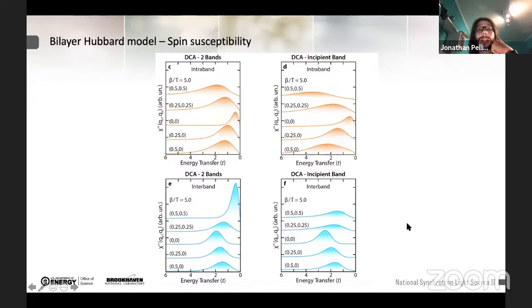What we could observe is that the intraband spin susceptibility presents the conventional dispersion of spin excitation in magnetic material, which has zero energy at the gamma point, at zero, zero, and then it increases in energy. Whereas the interband pocket presents an antiphase dispersion. But most importantly, look at the difference between the two-band model and the incipient band model: the susceptibility becomes hardened in the incipient band case, and the spin susceptibility, especially the interband susceptibility, which is the strongest one, becomes much flatter compared to the two-band case.